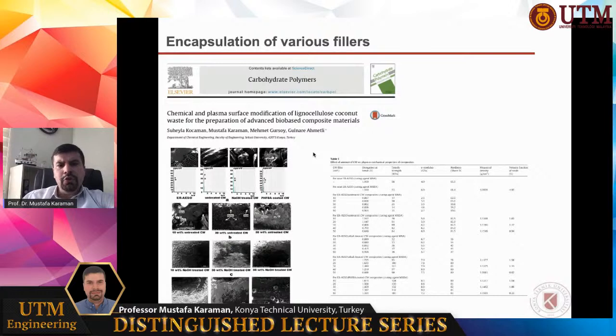Another example, encapsulation of various fillers. Chemical and plasma surface modification of coconut waste. A biomaterial surface can be converted to a useful surface as a filler material in bio-based composite materials with the help of CVD as well. Here we also deposited a thin functional coating by using our rotating bed PECVD system to make better composites, nanocomposites. To encapsulate the coconut waste, it's a particulate material, we use CVD, and we improved the mechanical and other properties of the composites with the help of CVD.